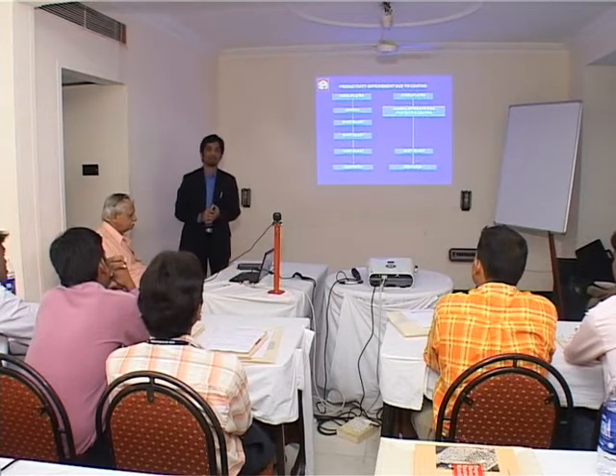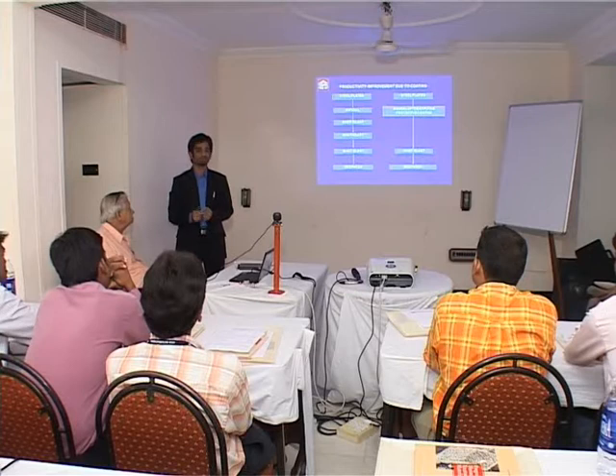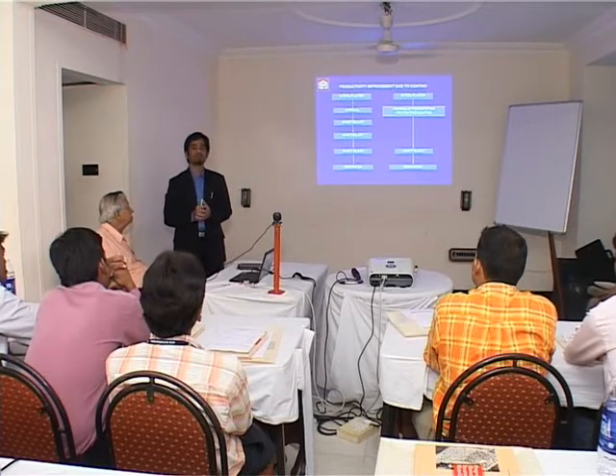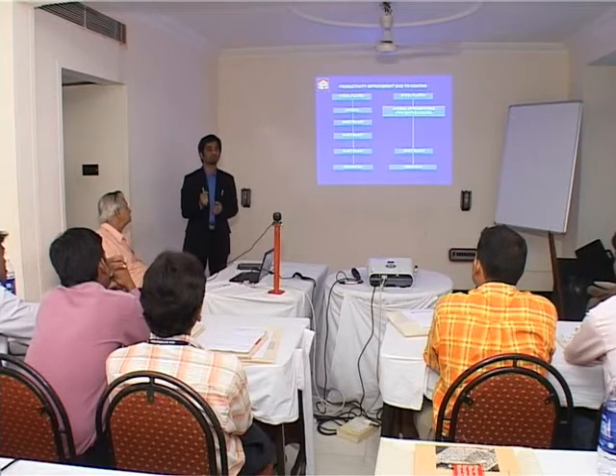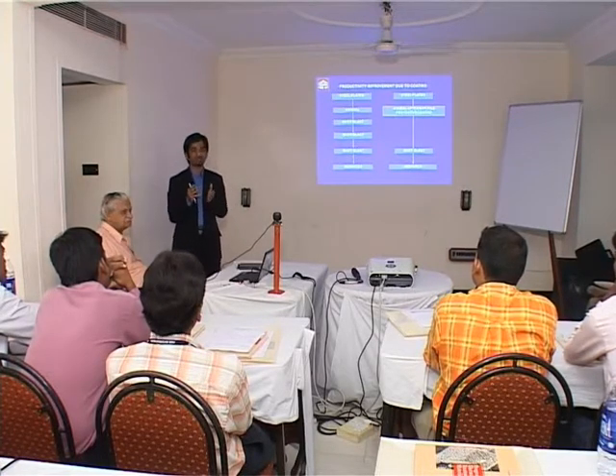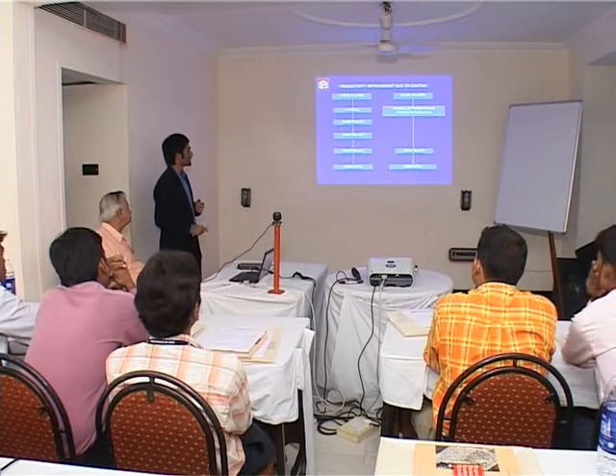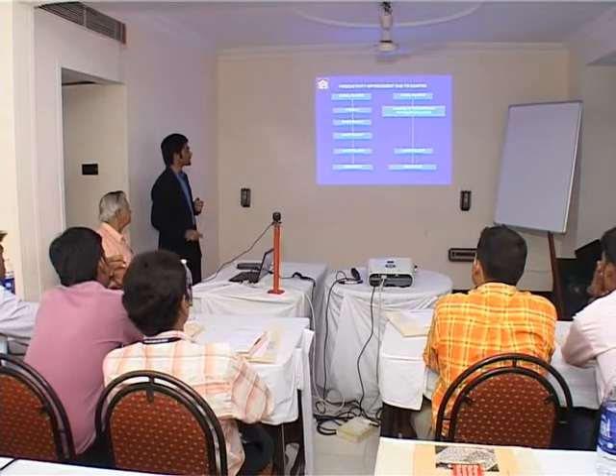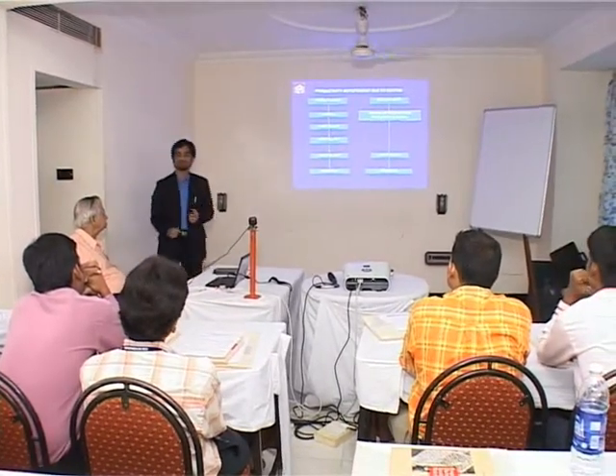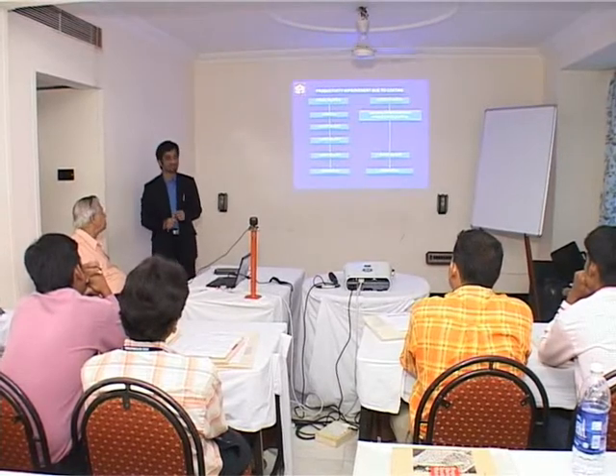This is a case study at Rourkela steel plant where the scaling was so adherent. I'm sorry, I don't have pictures because it was a confidential issue. The scaling was so adherent that they had to shot blast it 3 times. Can you imagine shot blasting 3 times for removing the scaling? And after using the anti-scale compound, very little shot blasting, once, and they could dispatch it. So in the post-heat treatment operation, we have a productivity increase of 66% almost when it comes to shot blasting.